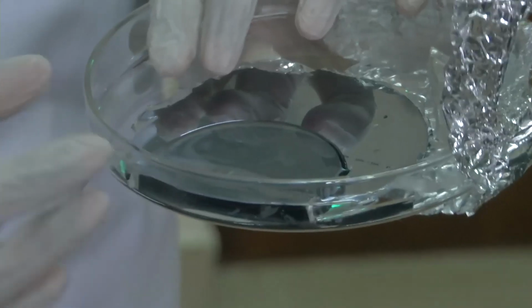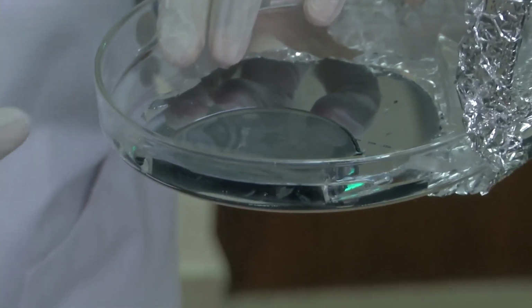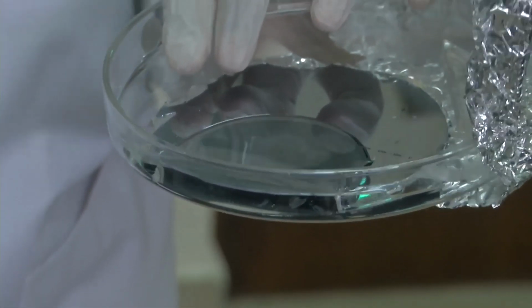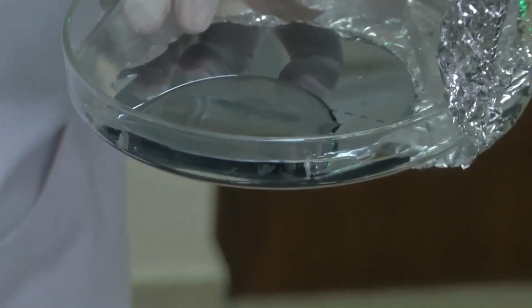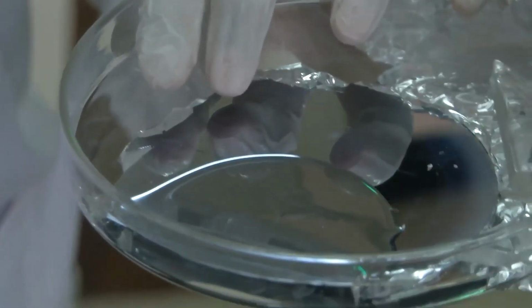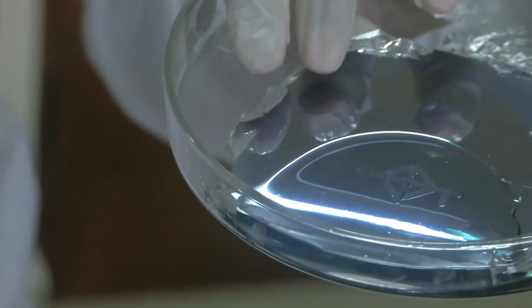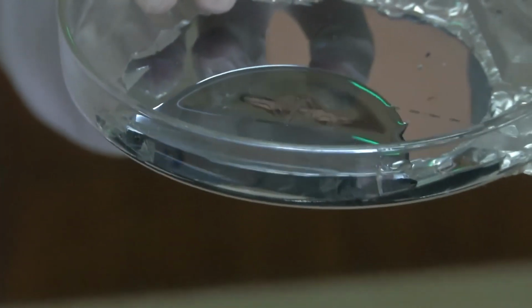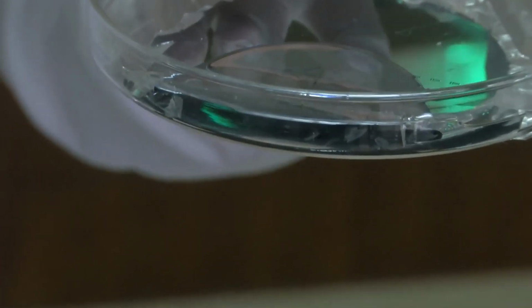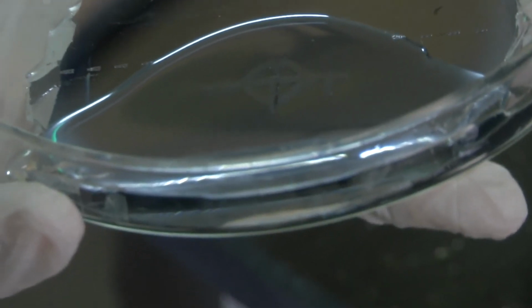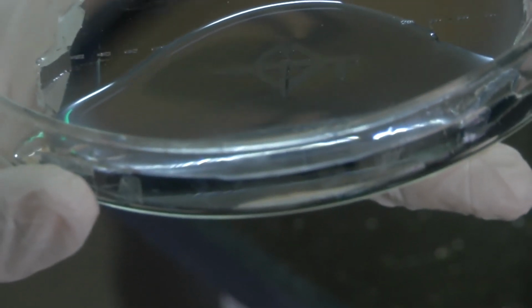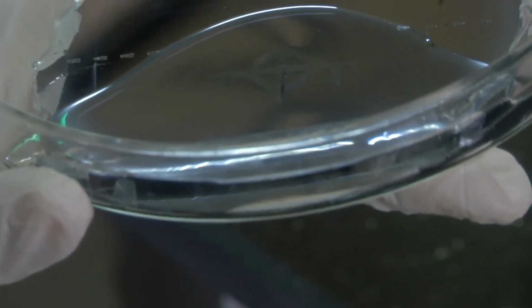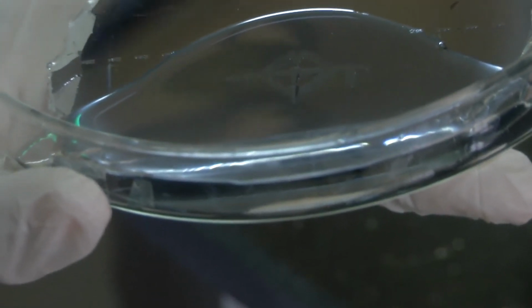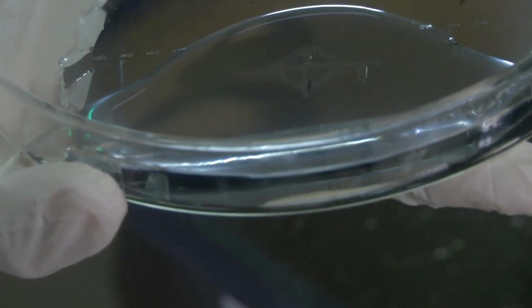There are absolutely no air bubbles, as you can see, and if by chance there are any air bubbles, you could remove them using a small needle. As you can see, this is the slight polymer mixture which I have poured onto the embossed surface on the silicon